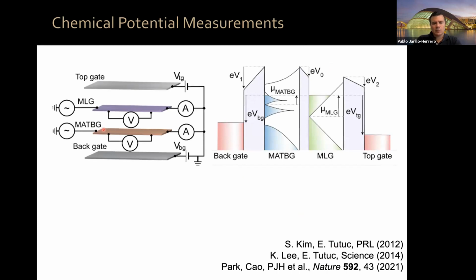So what we have is the following. We have magic angle bilayer graphene, and we have nearby, with an insulator in between, a monolayer graphene. It's going to be a sensor. This monolayer graphene is going to be a sensor of the chemical potential in the magic angle bilayer graphene. And we have a top gate and a back gate so that we can control the charge density in each of these layers, and hence the chemical potential in each of these layers independently.